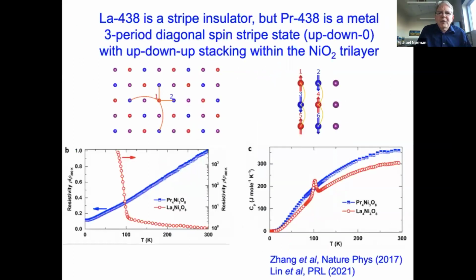So if you look at lanthanum 438, it's a stripe insulator, but the praseodymium compound is a metal. Interestingly, you get a 3-period diagonal spin stripe state, just like you get in 2,1,4 nickelates when you hole dope them. It has a sort of up, down, zero pattern. And within the trilayers, you have up, down, up stacking. That means you have antiferromagnetic coupling between the layers.